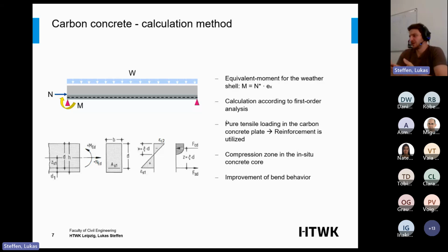But the calculation is like a simple steel reinforced beam, I would say. So it's a simple calculation, but with the in situ core we can improve the behavior, and we don't need high performance concrete for the in situ core. It can be done with a simple normal concrete because the zone is really high. So load bearing can also be done with less effective concrete.